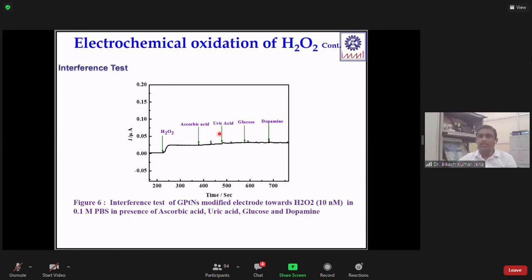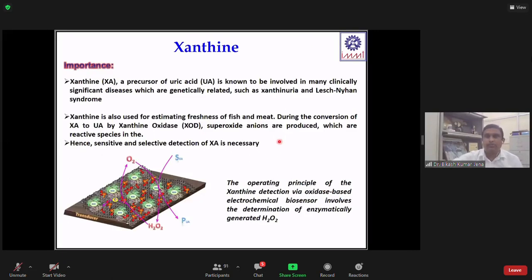We also tried to understand the interference test, that I have already discussed. For any electrochemical sensor, when you want to monitor some molecule, other molecules are there in our body, in biological samples. They may interfere or not. So in that case, for hydrogen peroxide detection, we added some ascorbic acid, uric acid, glucose, dopamine. We observed whether they play some role or not, but they are not playing any role. Because when you put the hydrogen peroxide, the current increases, but the other molecules do not respond with this kind of sensor, graphene and branched platinum nanoparticle.